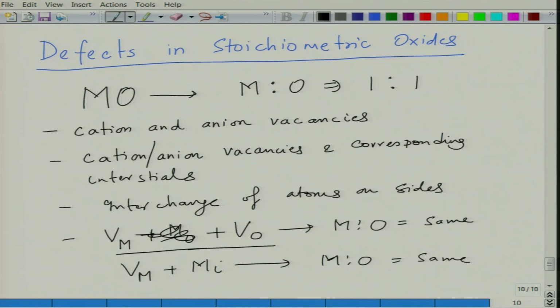These are various possibilities. You can also form interstitials, so you might have Oi and Mi without forming any vacancies. You bring in extra oxygen and extra metal, and both sit in interstitial sites without changing the stoichiometry. So many combinations are possible. Let's see a few of them. The first of these stoichiometric defects is called the Schottky defect.